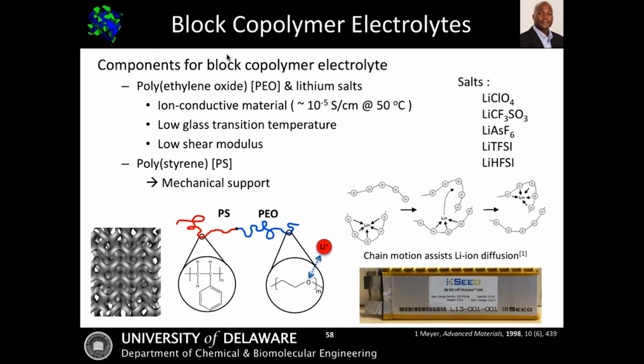So what I can do is combine this, or block it, with a mechanical support material, something like polystyrene, which gives me that mechanical stability, and in particular a modulus that's very close to that 7 gigapascal limit. The first part I'm going to talk about is salt-doped polymers, and in that case you need to take this polymer and dope it with a lithium salt so that I have the lithium available for lithium ion conductivity.